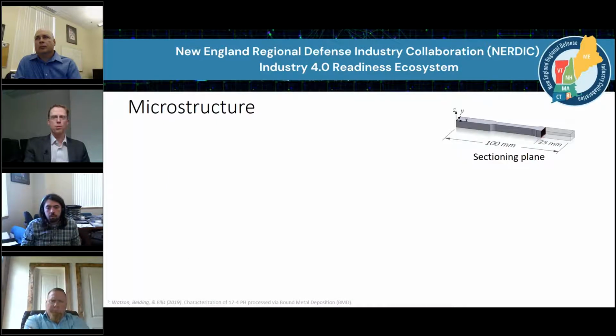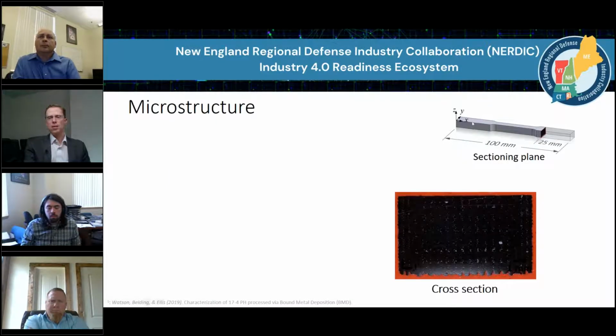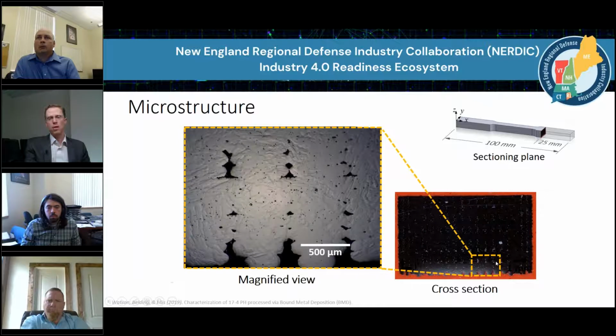If we look at the microstructure, here is a tensile coupon from some tensile specimens we ran. This is the cross section. We take a close-up look at that one particular cross section. We see all these types of voids, and so we end up with these inter-raster pores, which are pores that occurred between 2 rasters, and then we get intra-raster pores, and that's just due to the shrinkage and the ability to take these particles and form them into a solid. You get a little bit of pore that remains.